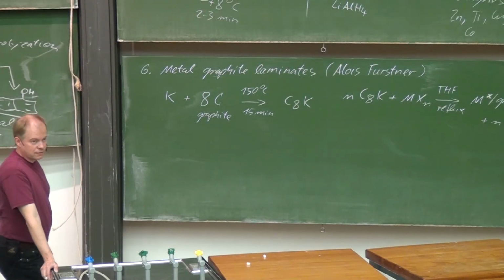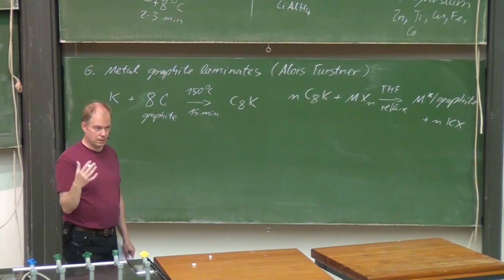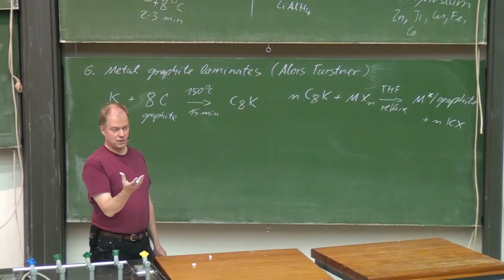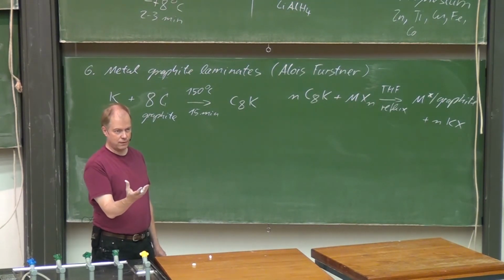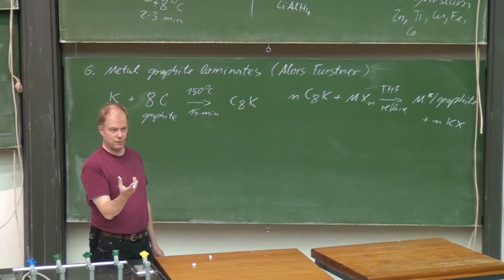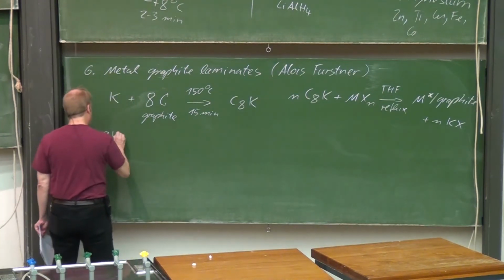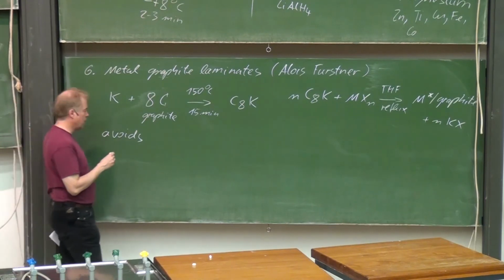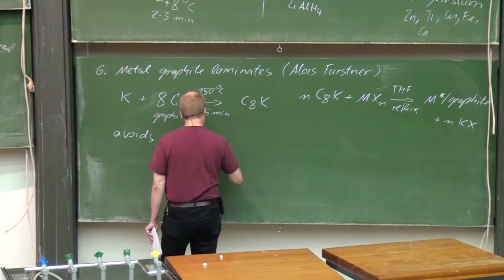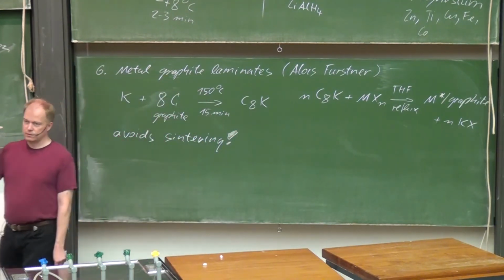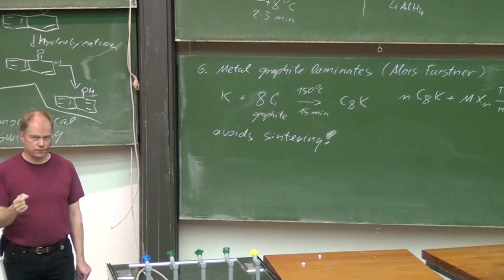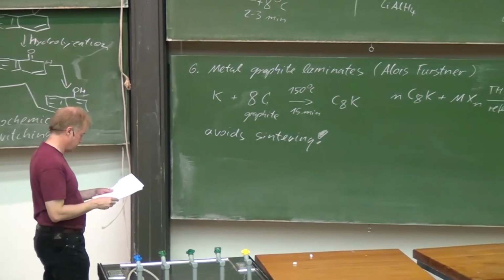You will notice that advantage if you form Rieke metals and wait some hours or days before you apply the Rieke metals. The small particles as Rieke metals can move within your reaction flask, and if they get together, they will glue together. Okay, they form aggregates. This process is called sintering. So, Fürstner's method avoids sintering, because the small metal particles are sitting on the surface and they just don't move, so they don't get together.